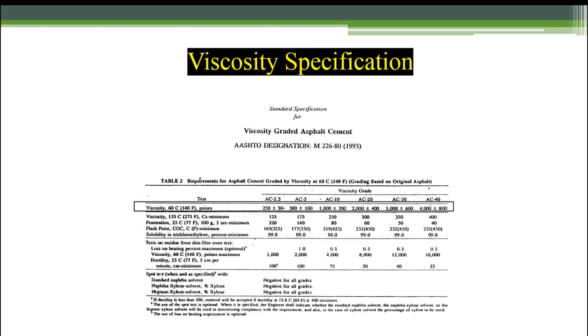And you can see that pen grade right below it. And as you would suspect for the lower viscosity grades, the penetration numbers work the opposite as well. Lower viscosity, softer material, penetration's 220. Higher viscosity material, AC40, the penetration minimum was 40. So just then tests on residue and so forth. So those are kind of your takeaways from that.